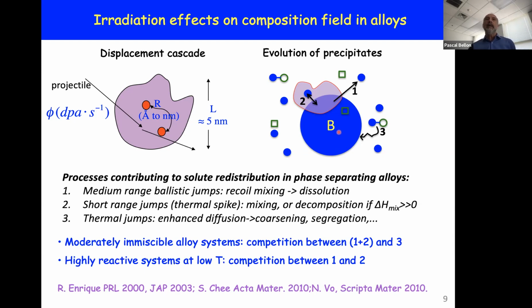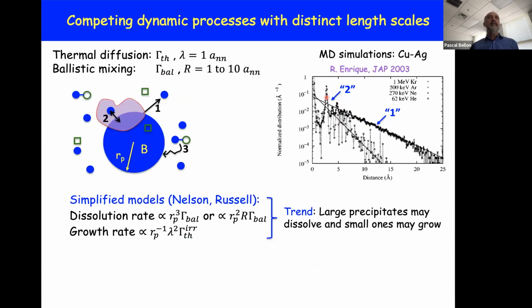In a moderately immiscible alloy system, mechanisms 1 and 2 lead to dissolution, and mechanism 3 to coarsening or renucleation and precipitation. So there's a competition between these mechanisms. In highly reactive systems, even in the absence of thermally activated migration, we'll see that just 1 and 2 can compete with one another, and this is important for self-organization.